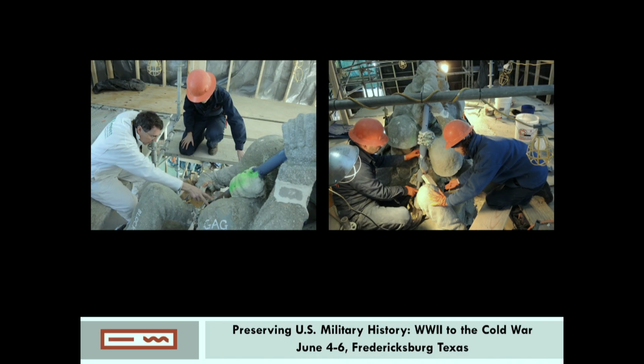The interior of the pole was filled with loose corrosion products, and they were taken out, and that was cleaned. It was then reattached to the sculpture with 5 pieces of number 3 rebar, which were grouped together for structural support. This was 2 feet in length. It was secured in place with structural epoxy. And then Craig Bennett is our engineer on this project on the left there, and he's advising us on that before we cut the pole.